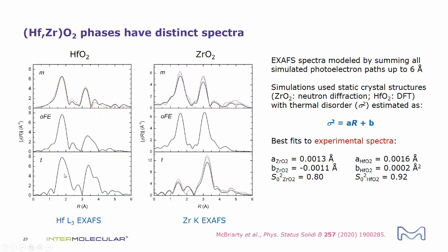Oh, sorry, I think it might have been actually much less separation. So we end up with a peak which sums the 2 nicely. With zirconium oxide, we actually have a bit more separation between the short bonds and the long bonds. And we end up with destructive interference in the Fourier transform, which gives us very little magnitude in the Fourier transform. So this is a great example, I think, of how your Fourier transform is not a radial distribution function because of interference effects, and that's glaringly obvious in this case.